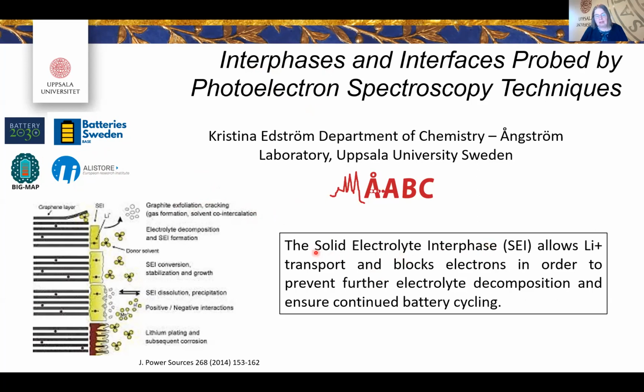And this solid electrolyte interphase is primarily formed on the negative electrodes in lithium batteries, in sodium batteries. And interfaces are formed in every battery, of course, but in this case, it's a bit thicker, it's a bit more complex. It's a mixture of different compounds. And it's actually a necessity specifically for lithium-ion batteries where we have graphite as a negative electrode. And it's really the prerequisite why graphite electrodes work for lithium-ion batteries.